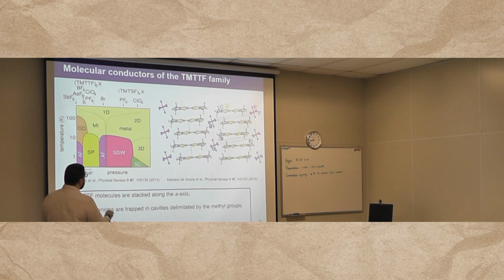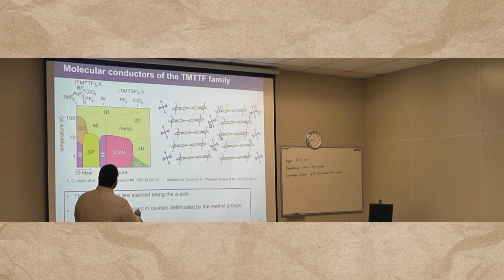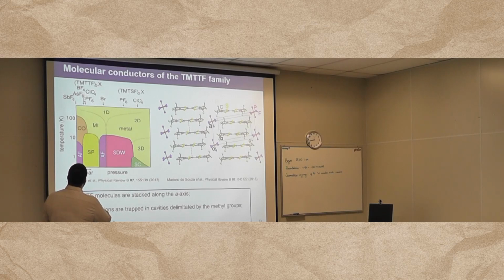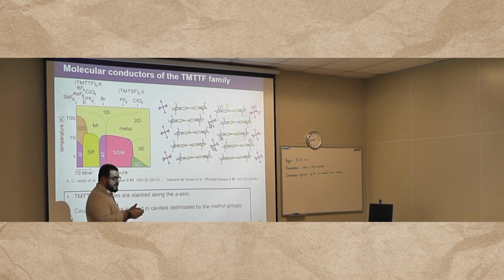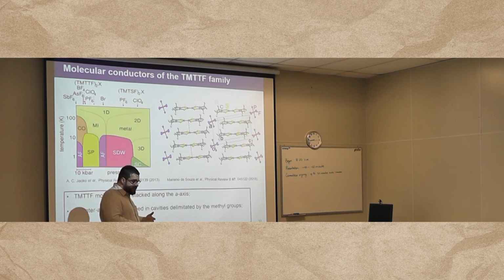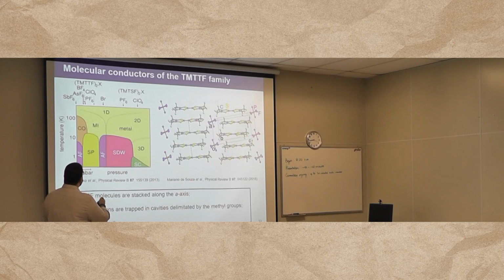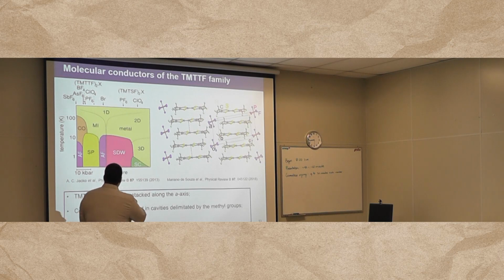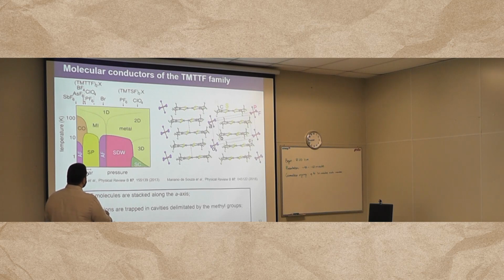That's why it's TMTTF2X. The unit cell is triclinic. And then we have the cavities that incorporate a centrosymmetric counteranion, which can be antimony fluoride 6, arsenic fluoride 6, or phosphorus fluoride 6. And the nice thing here is that the systems are very crystalline because they are synthesized by an electrochemical process. And also, if you change this counteranion, you change the so-called chemical pressure on the lattice, and that's why each system starts at a different pressure without applied pressure. And this is very important because with this system we can explore various types of phases, and also superconductivity, which was discovered first in TMTSF2PF6 under pressure.